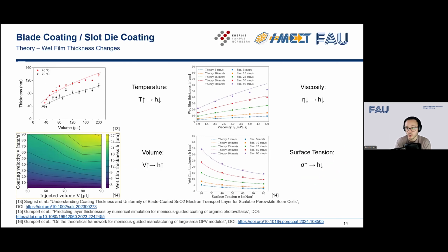The other thing we can do is play around with the volume. As you can see on the bottom left, the volume has a direct impact on the thickness of our coating because it directly affects the receding meniscus. The more volume, the higher the meniscus, the higher the dry film and the wet film. The viscosity plays a quite big role. The lower our viscosity, the thinner our layers will be. And for the surface tension, the higher the surface tension, the thinner our layers will be in blade coating.